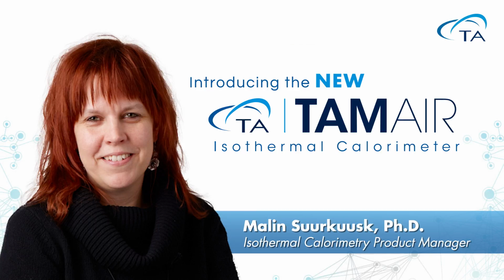Yes. You can either do one experiment with all 8 channels together, or you can start every channel independently of each other. The only thing they would have in common is the temperature, as they sit in the same block. But you can start every experiment at different times or as single experiments, or you can also combine 2 channels in each experiment. That's also possible. The only thing is, if you're measuring very, very small amounts of heat, you would like to start them close in time to each other. For a cement sample, it doesn't matter at all because there is so much heat involved in the reactions we are looking at.